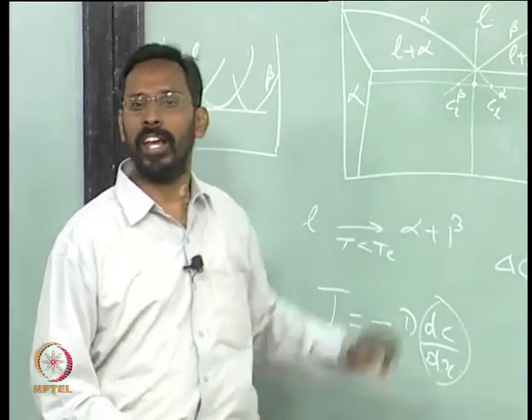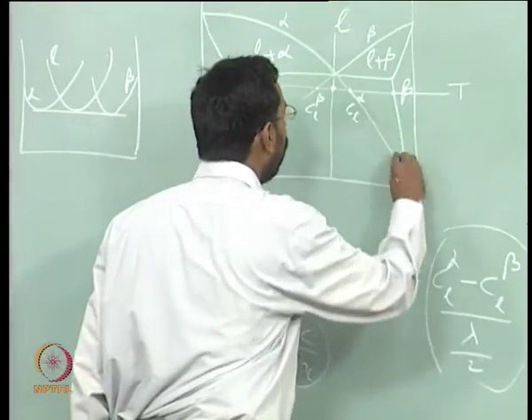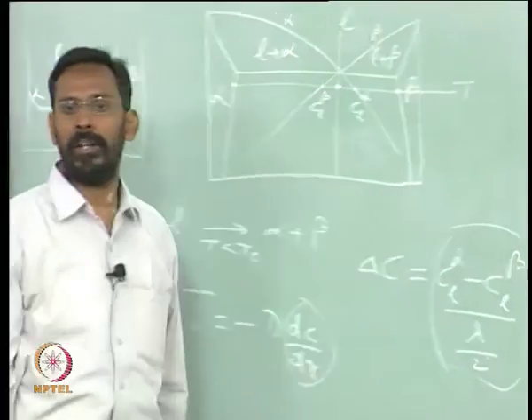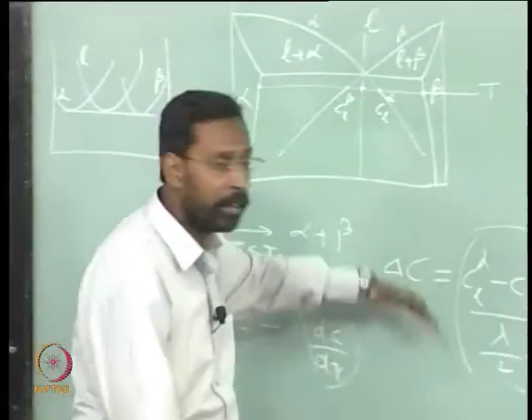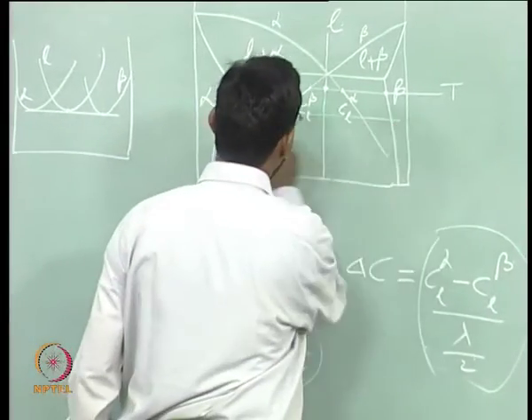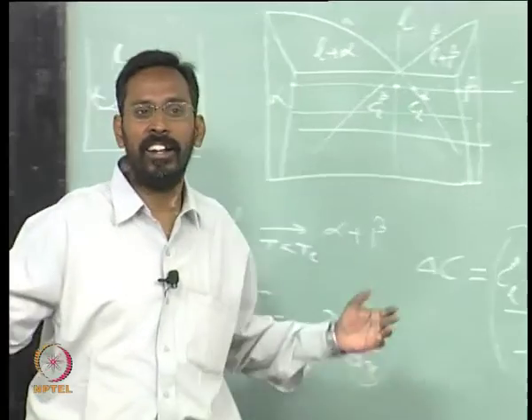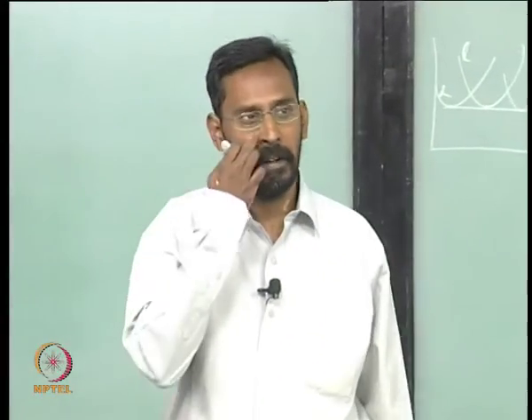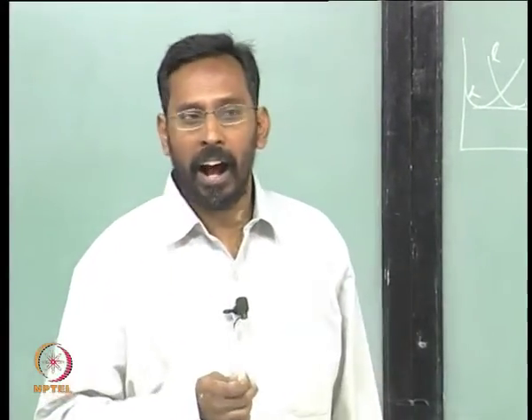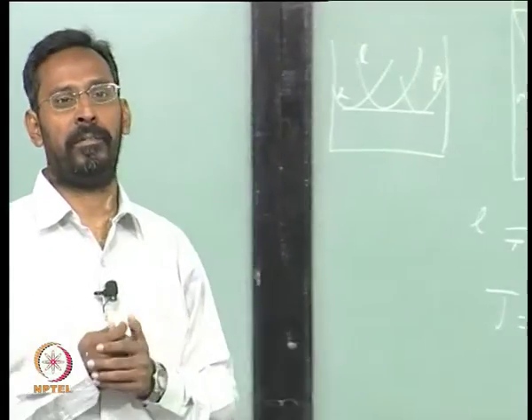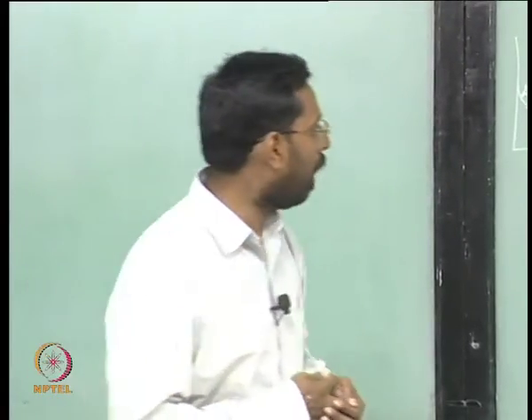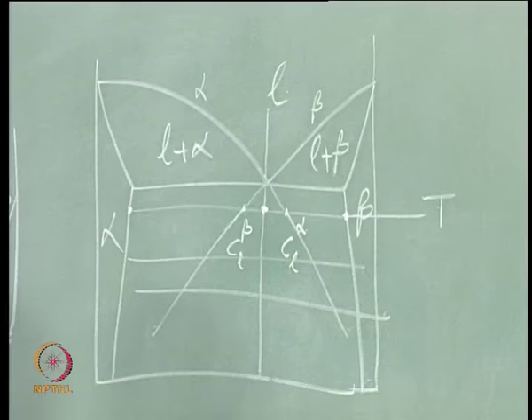And that is why you can again see that if I extrapolate this to lower temperatures, the lower the temperature, the larger the delta C, am I right? That means the larger the gradient, and as a result, in principle, the growth rate has to be higher. But there is a catch here. What is the catch?